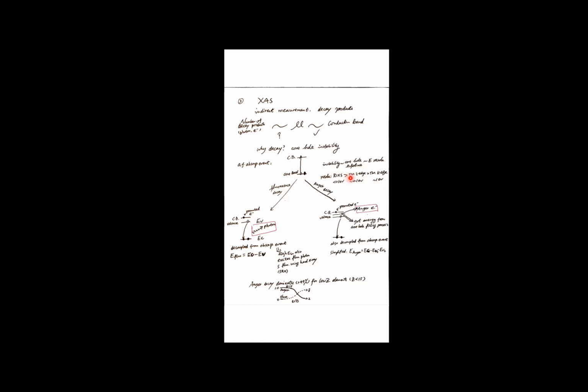But if this is a transition metal L-edge, it is a 2p hole, because we're talking about the 2p electron excitation. Then the 2p hole lifetime is much longer than the K-edge core hole. So the energy resolution for the L-edge spectrum is better. And if we have a very nice instrument, for example, at ALS, then we can go to about 0.1 eV energy resolution, meaning that we have some very, very well resolved peaks in the L-edge spectrum. But if we do RIXS, then it can be even further improved.